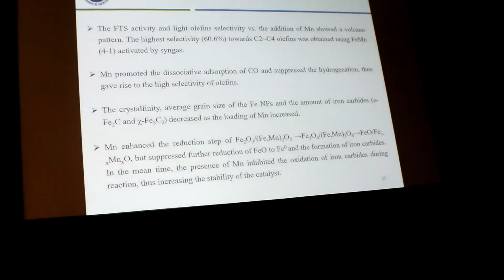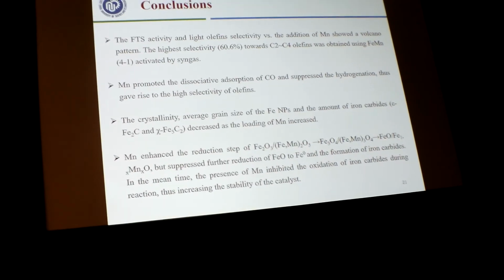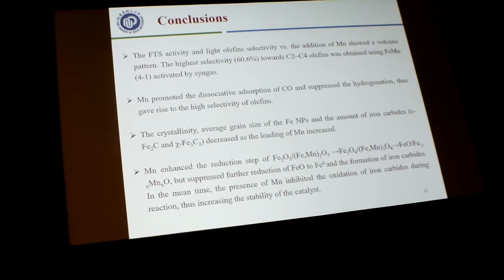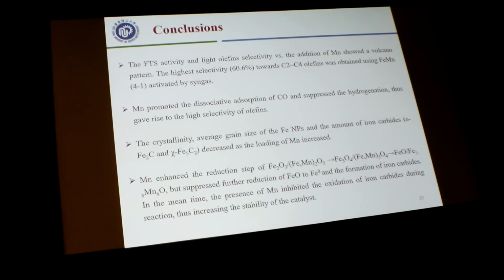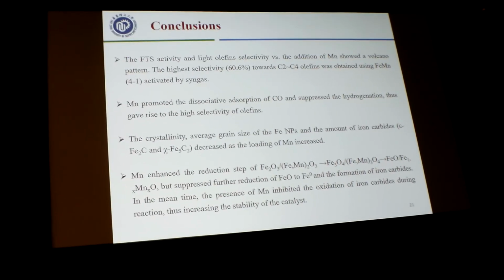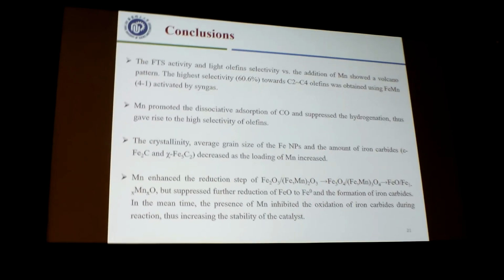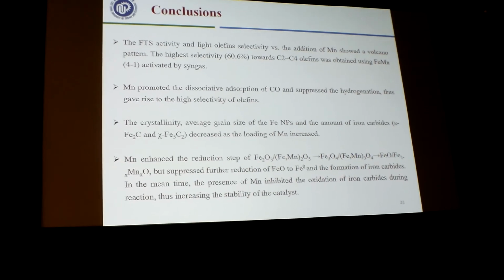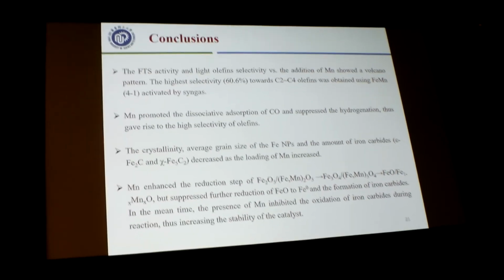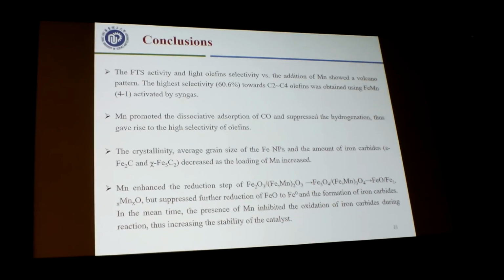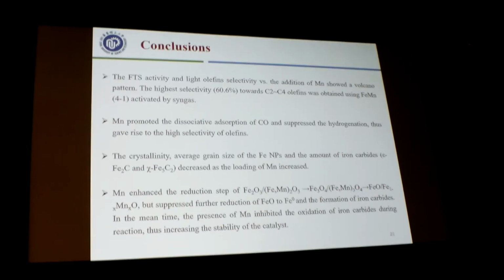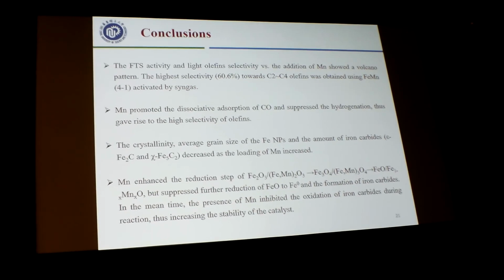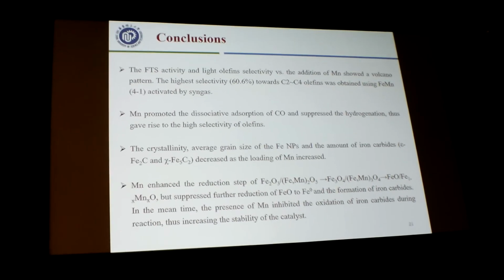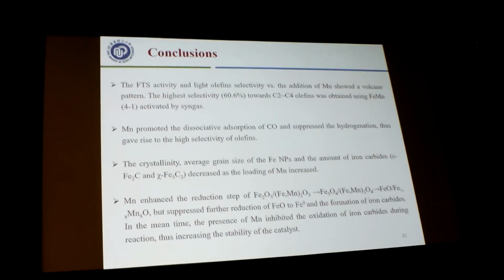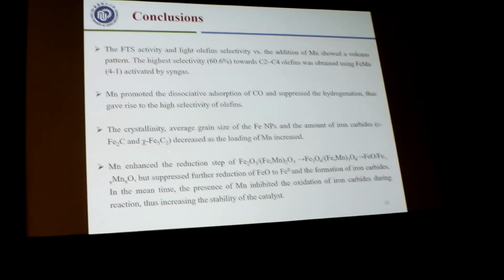And the conclusions here is the FTS activity and the light olefins selectivity versus the addition of manganese showed a volcano pattern. The highest selectivity of 60% for C2 to C4 olefins was obtained using manganese promoted catalyst with a ratio of 4 to 1 activated by syngas, and manganese promoted the dissociative adsorption of CO and suppressed the hydrogenation, which gave rise to the high selectivity olefins.